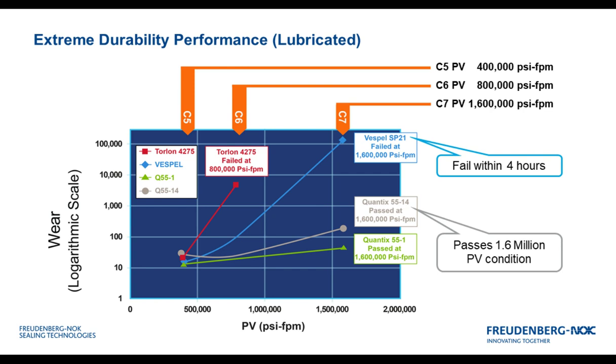If I again move to doubling that to the C7 condition, this is a 1.6 million PV value. We see the Vespel materials will not pass a 4-hour test, and you can see the example of the Freudenberg materials. They're both doing very well. We accomplish this by clearly understanding how the failure modes occur. By knowing what the fillers can do, we can develop these materials to have extremely high condition and operating performance.